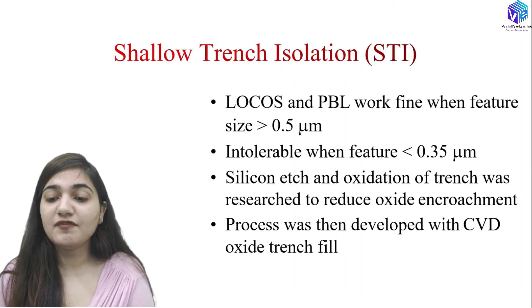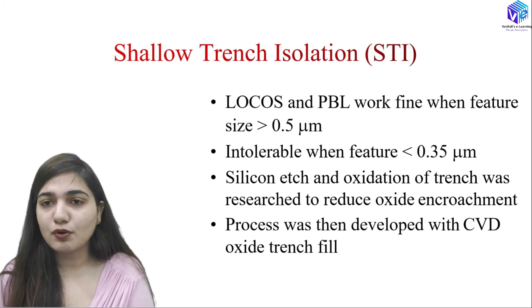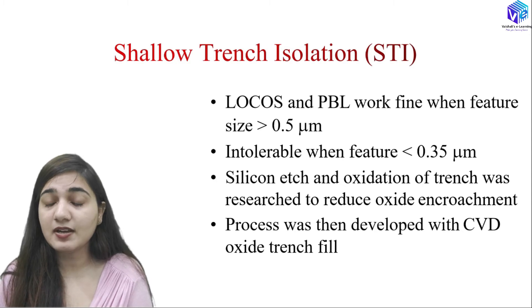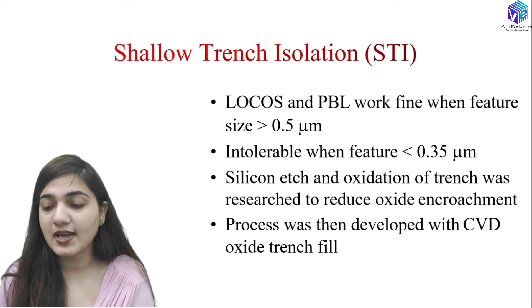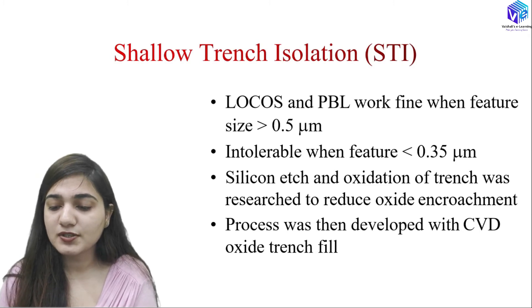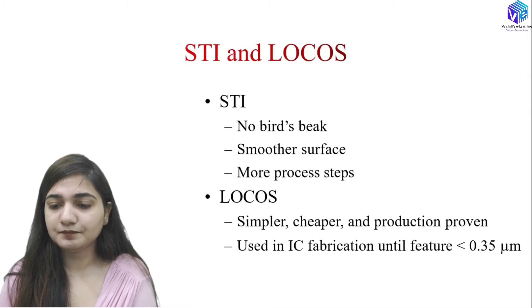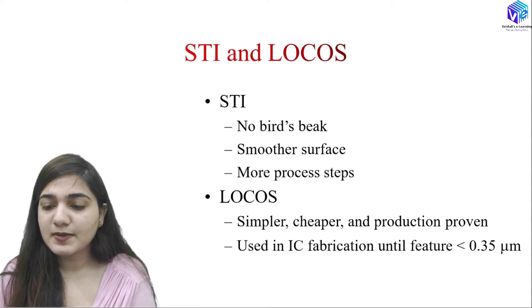Now coming to shallow trench isolation (STI). LOCOS and PBL work fine when the feature size is greater than 0.5 micrometers, but when the feature size is less than 0.35 micrometers, these two methods are intolerable because the active area is going to reduce a lot. Silicon etching and oxidation of the trench was researched to reduce oxide encroachment, and a new process was developed: STI with CVD oxide trench fill.